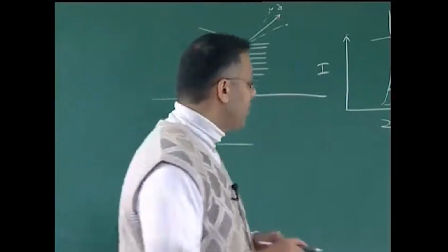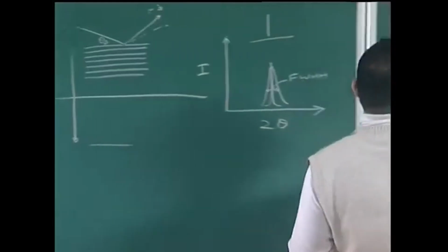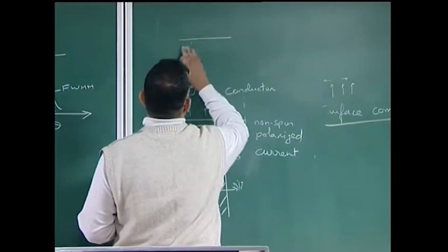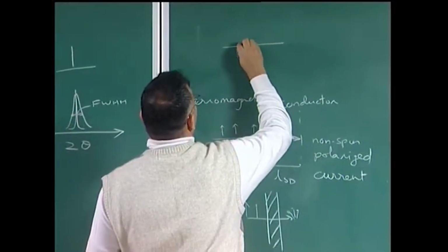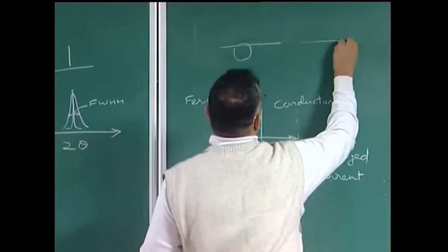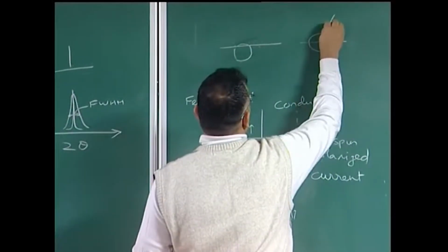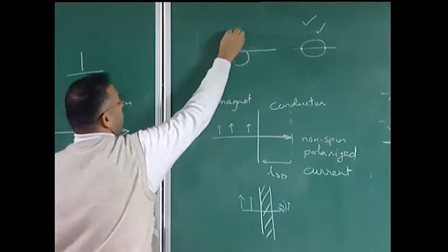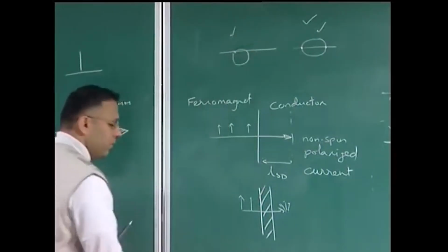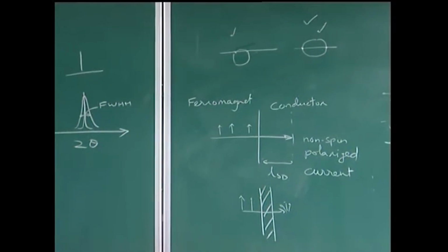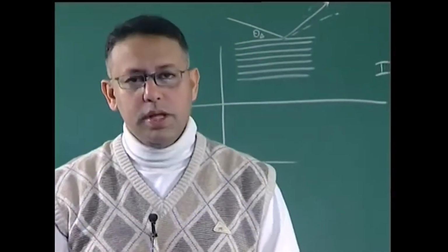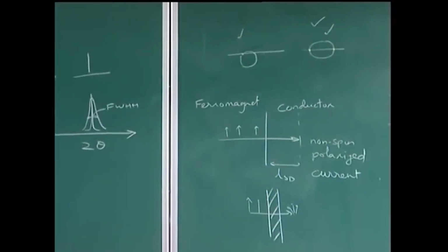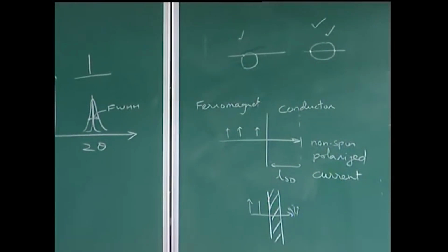It is seen that those particles which have a larger perimeter of support, for instance, suppose I had two gold particles, one like this, and the other one. So, this has a larger perimeter of support, and this shows higher catalytic activity as compared to this which has a lower perimeter of contact, which will show lower catalytic activity. Therefore, clearly gold is becoming catalytic at the nanoscale, but the role of the interface or the support structure is also playing a very profound role in the whole property.